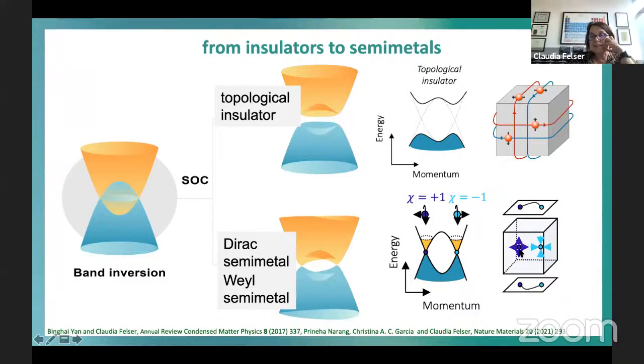And this can lead to very special properties here, as you maybe already know as a theoretician. We can have, it's not as nice as it should look here, this in the bulk electronic structure of this material, these so-called Weyl points, which act like monopoles. Because of the different chirality, we also have different properties of the Berry phase, and this leads also to this Fermi arc kind of surface states.